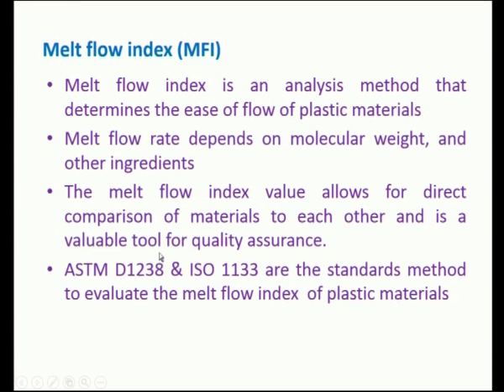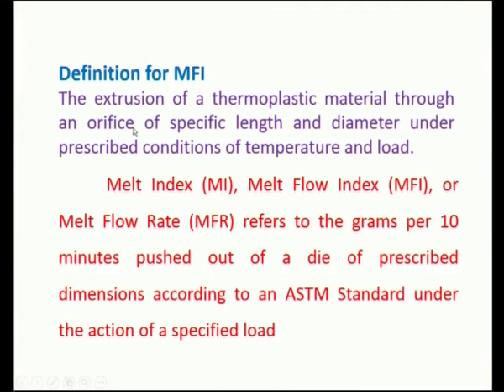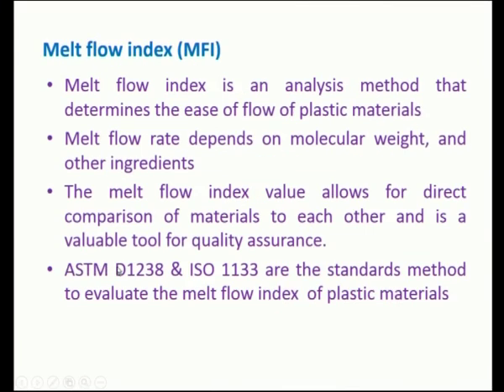The melt flow index value has to be evaluated based on these two methods. Of course, the ASTM D1238 method we will see in the next slide. Before that, what is meant by melt flow index? The melt flow index refers simply to the extrusion of a thermoplastic material through a very small orifice of specific length and diameter under prescribed conditions of temperature and load. So ASTM D1238 and ISO 1133 are the standard methods to evaluate the melt flow index of plastic materials.